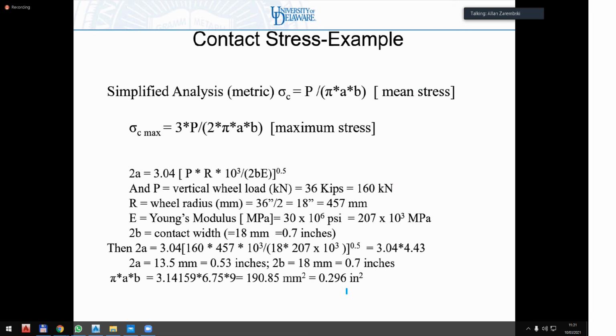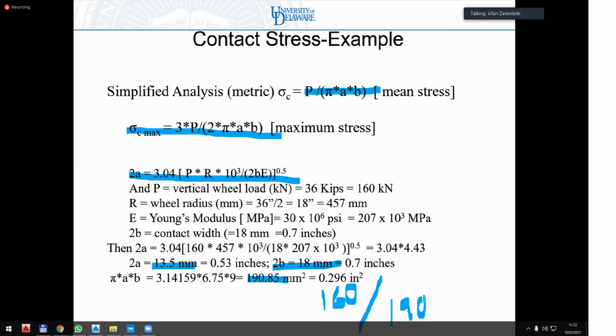So again, if I can calculate 2A, in this particular case, let's say 2A is 13.5 millimeters, 2B is 18 millimeters, the area is pi AB, which is 190.85 millimeters squared. My average stress is P over pi AB. So if my wheel load is 160 kilonewtons divided by 190.85 millimeters squared, that'll give me my average stress. My maximum stress is 1.5 times that.